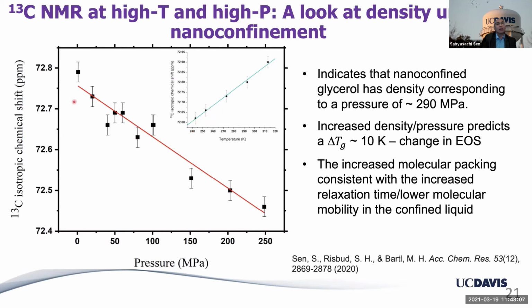So you see they go in different directions, and their slopes are consistent with the corresponding thermal expansion coefficient versus bulk modulus of glycerol, which shows that chemical shift is indeed controlled by the density of the glycerol. So in that case, the bulk glycerol chemical shift is somewhere here, obviously at 0 MPa. But the confined glycerol shift turns out to be here, which says that the nano-confined glycerol has a density corresponding to a pressure of about 290 megapascals.